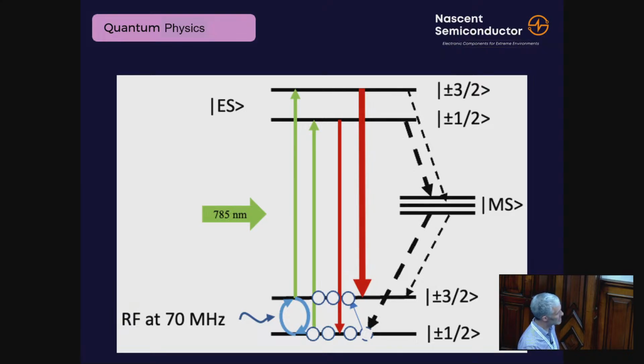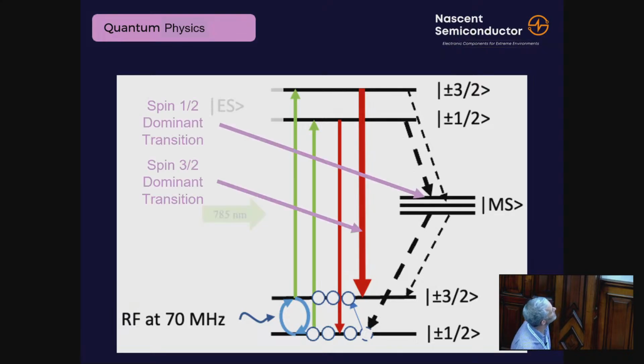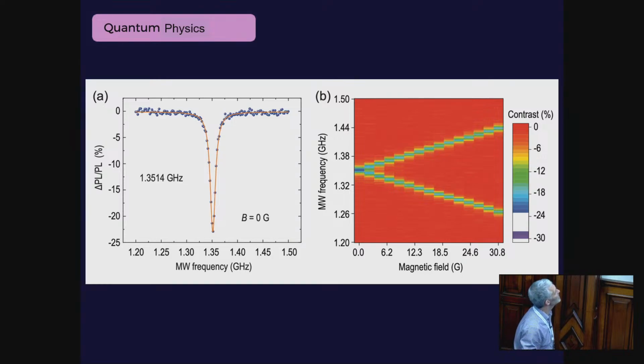And so if we're doing this for real in an experiment, well, those are our two dominant transitions. In order to measure it, we want to populate the spin 3/2 state, so we apply this RF signal at the bottom. And what we do is we sweep the RF field, and when we get to the point where RF equals 70, we see a nice big spike in our resonance. Ta-da, that's quantum.